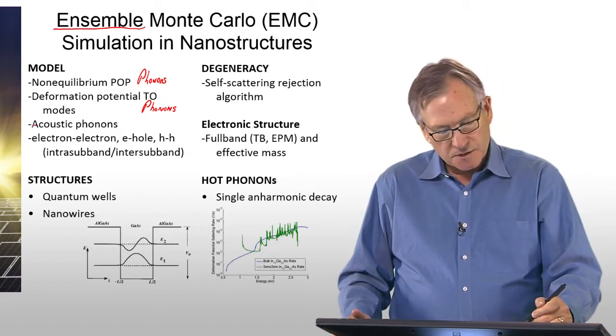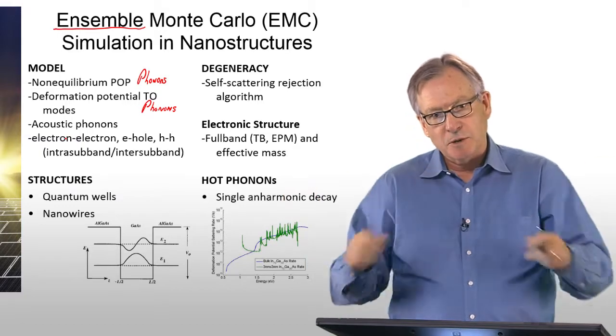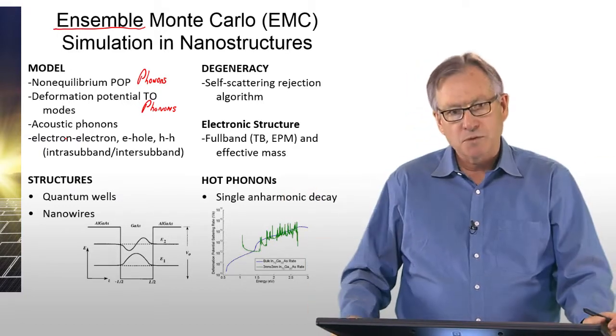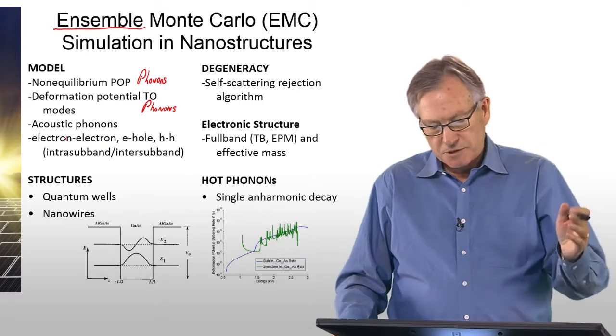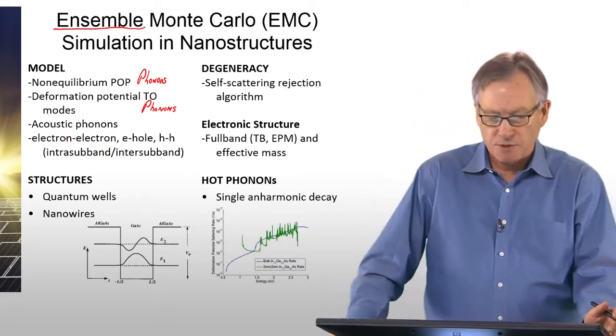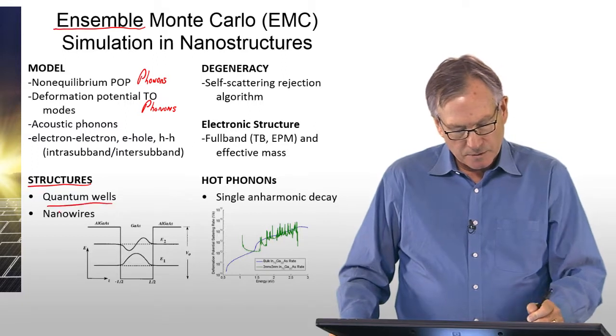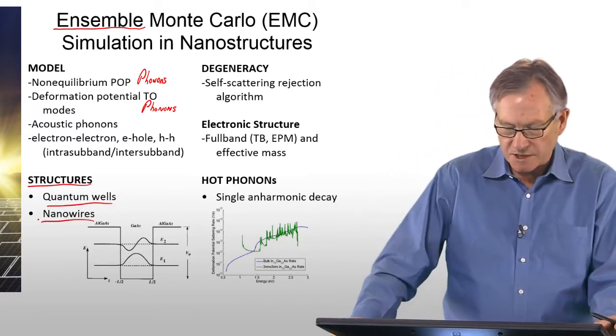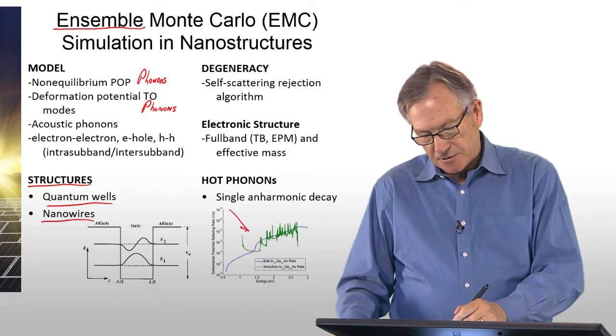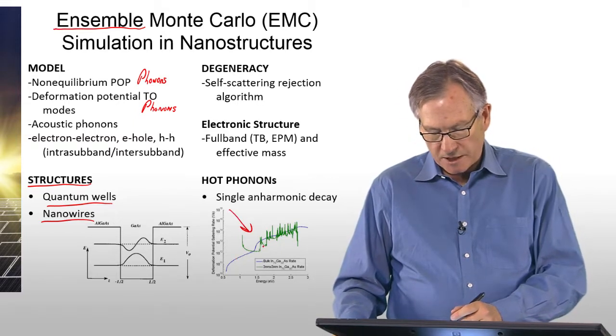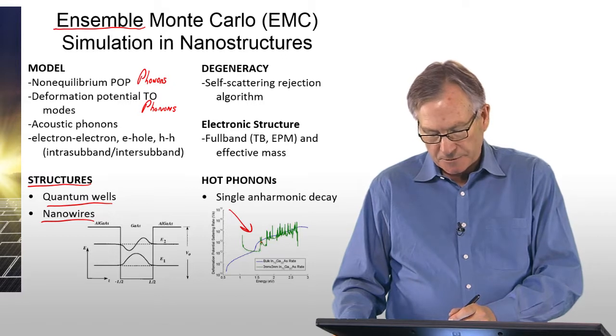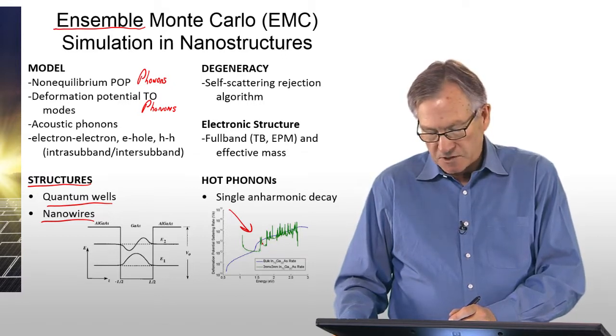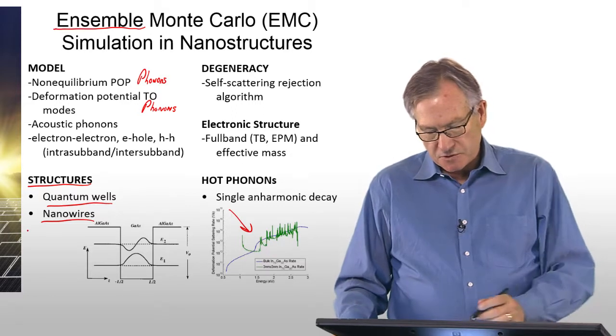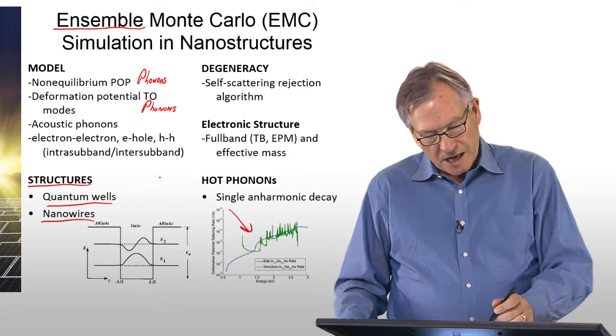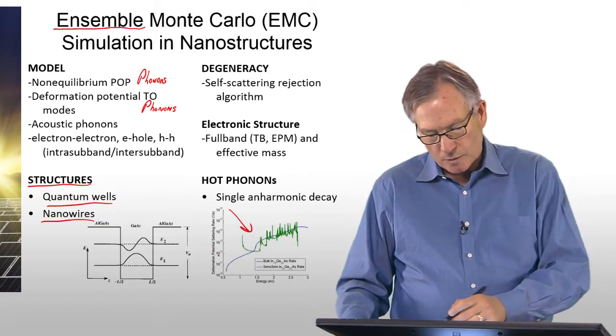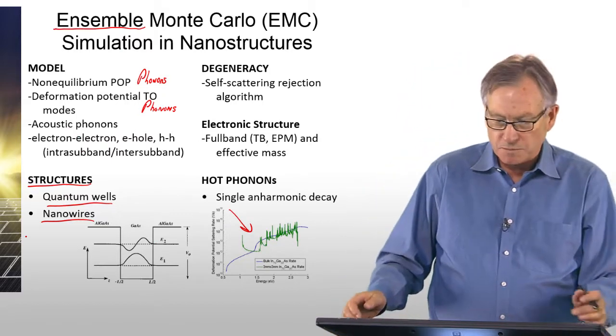So there's different kinds of phonons that interact. The electrons can scatter amongst themselves. They can scatter with the holes. They can scatter in a bulk material, or they can scatter in a quantum confined system. So a lot of what I talk about has to do with nanostructured systems such as quantum wells and nanowires, in which we calculate the scattering rates. This is a comparison of the bulk scattering rate in blue, and the green scattering rate is that of a self-assembled nanowire of indium arsenide, just to illustrate that these scattering rates can be calculated either in bulk or for nanostructured systems, which is what we do.